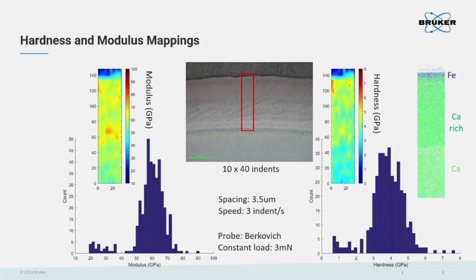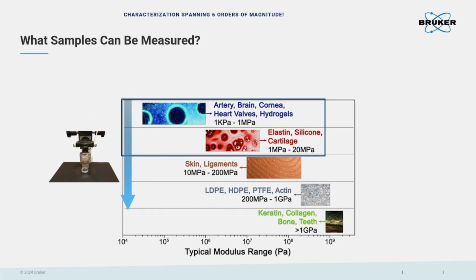So it is a very good correlation if we have suitable resolution with the hardness and modulus. And it is not very difficult for us to use our nano indenter to make the indentation array. Then we can have these very highly correlated mechanical property distributions. So we can combine the viewpoints of the mechanical properties together with the chemical element distribution. Okay, so these are the two examples I would like to share with you, talking about biomaterials, actually biocomponents, composites with higher mechanical properties. Then we can move to another region of the mechanical properties with a very low modulus.